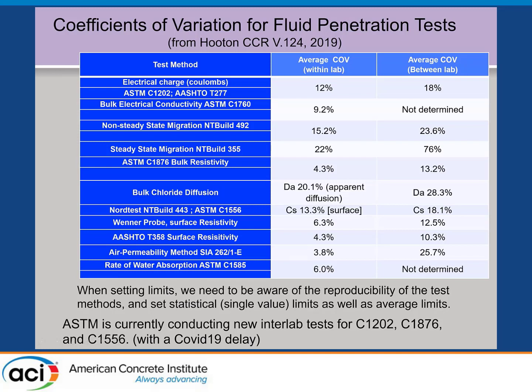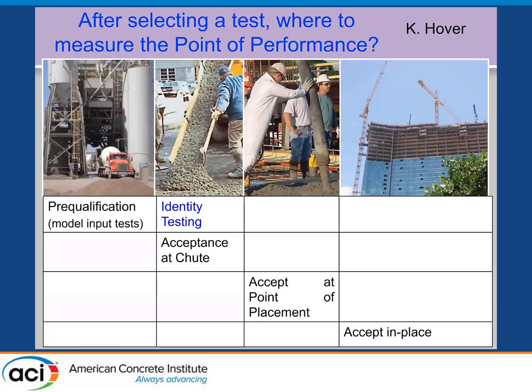So, okay, we have test methods, we have exposure classes. When do we test? And I took this from Ken Hover. We want to pre-qualify mixes. We want to have information on how good the mix is before, when you're bidding on a job. When it arrives on site, you want to do some testing to identify that it's the same concrete you pre-qualified. And then often we do acceptance at the chute. We do cylinders and whatever else at the chute for acceptance purposes.